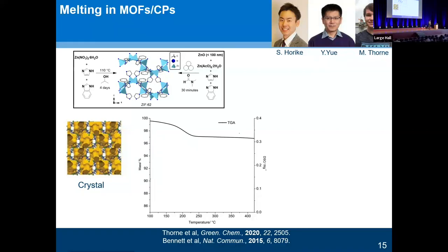The first reason, what happens when you heat this material to 200 degrees, 4 hours? What happens when you heat it to 270 for 9 hours? What happens when you heat it to 350 for 30 minutes? What happens when you use air, when you use nitrogen, when you use argon? This experiment tells you nothing about that. So to start thinking about the thermal stability of MOFs, and these have exceptionally high thermal stabilities, with just a TGA, you know, that really needs looking at in this field.